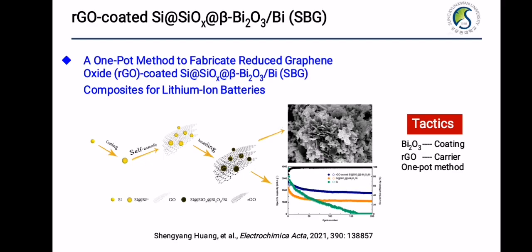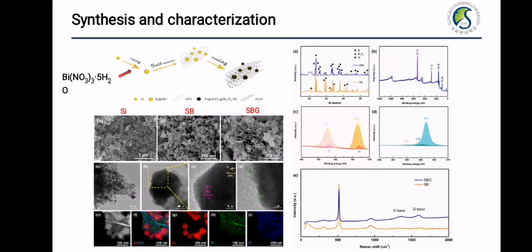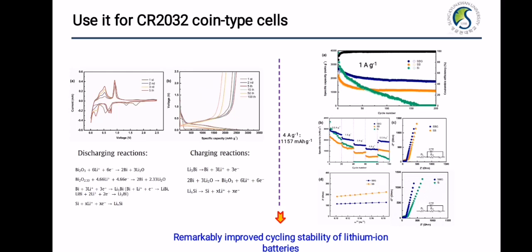In SEM and TEM images, we can see the silicon nanoparticles were well coated by bismuth oxide and flower-like reduced graphene oxide. And the XRD patterns, XPS spectra and Raman spectra also confirm the existence of bismuth oxide, bismuth, and reduced graphene oxide. In CV curves, we can find the typical peaks of silicon and bismuth oxide, which are linked to the discharge-charge profiles. We can see that there are some discharging reactions and charging reactions.